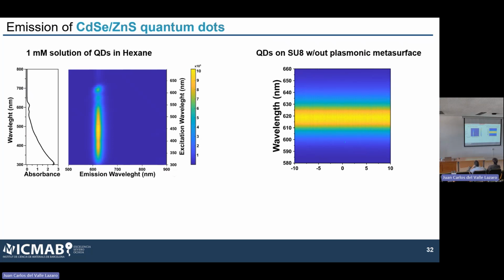And this is the angular characterization in emission. In this case, the detector is always normal to the sample, so what we're doing is twisting the sample. But anyway, what you need to pay attention to here is that we don't see any angular dependence, as expected, because this is just quantum dots.